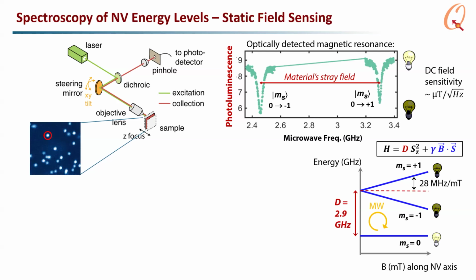Okay, so the typical experimental setup looks something like this. It's a confocal microscope where I can focus laser light down to a micrometer spot and raster it on the sample. The samples we use, if it's a bulk sample, are really, really pure, so part per billion defects, such that the spacing between 2 defect centers is bigger than the optical spot size. So if we shine our laser at one of these spots and then drive a microwave between the ground state transitions, every time we hit a magnetic resonance, the spin gets driven to the m sub s equals plus or minus 1, and we see less fluorescence coming out from the sample. So the splitting between these two states gives us the material's stray magnetic field.